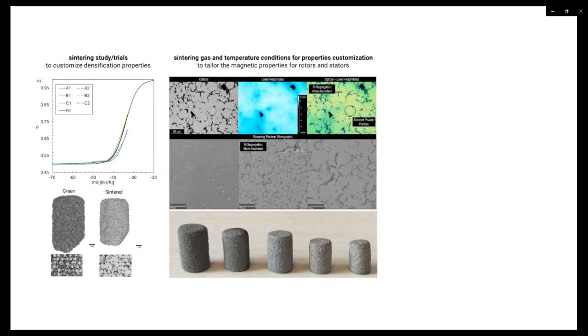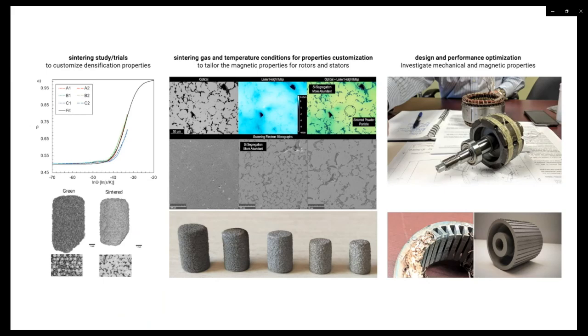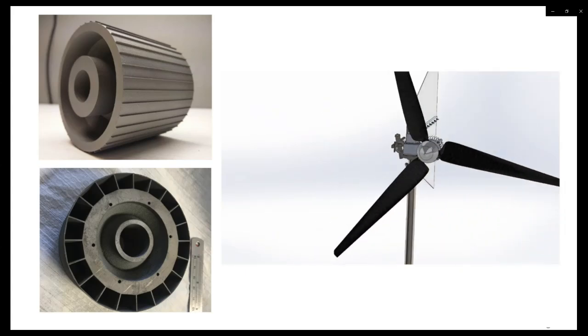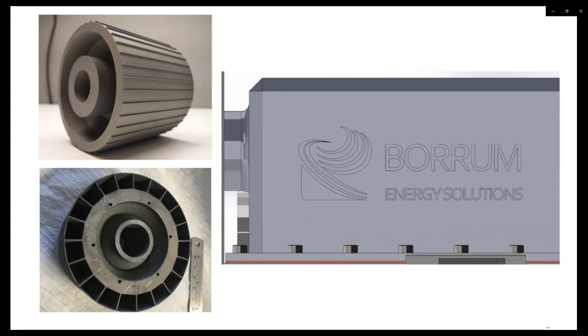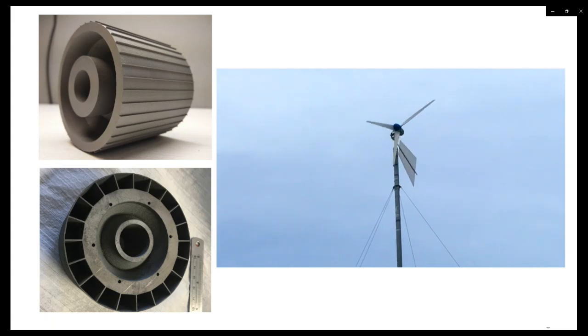For soft magnetic materials, for instance, the MSEM Binder Jetting Research Group have developed densification models to predict the shrinkage during sintering and determine geometric compensation factors to obtain shape fidelity, and are in the process of developing specialized heat treatment schedules to attain specific magnetic material properties. The ability to control the heat treatment schedule during densification is unique to the binder jetting additive manufacturing process and shows promise in manufacturing generator components. We hope that additive manufacturing technologies, and binder jetting in particular, will provide competitive advantages in the energy sector, specifically for small-scale power generation.